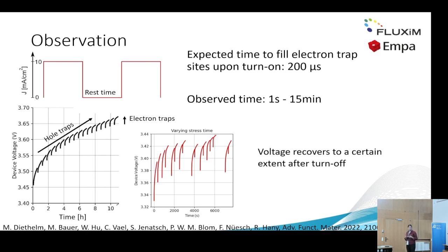And just to see that we don't have a substantial amount of hole traps forming, this experiment took place in about the same time frame as this experiment, and we have a lower increase in device voltage. And also what we can see is a significant recovery when we rest the device and do not apply any constant current.